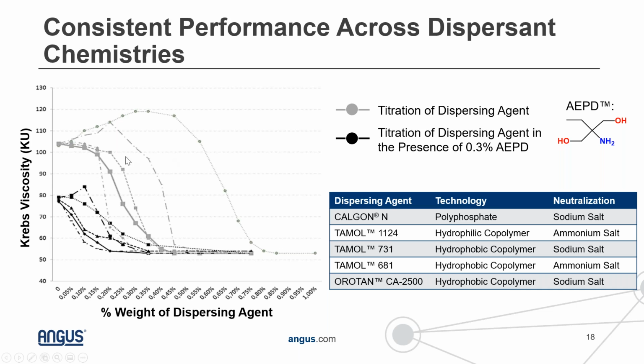But regardless of the dispersant chemistry, what we see is that for the titrations of just the dispersing agent itself, which are in light gray, compared to using 0.3% of AEPD, we see much lower viscosities and much better quality grinds achieved with using AEPD as an amino alcohol to help co-disperse these dispersants. And we see that regardless of dispersant chemistry.